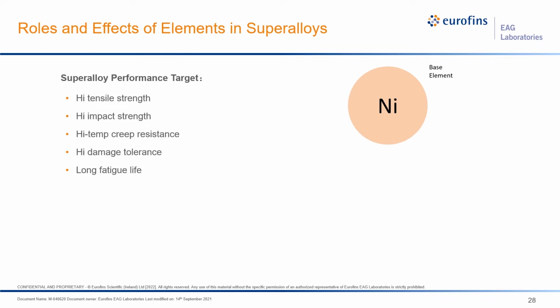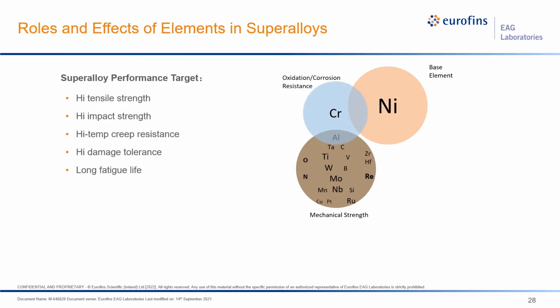Superalloys are used in a high temperature, high oxidation environment, so there are certain performance targets. They are nickel-based alloys and need to achieve high tensile strength, high impact strength, high temperature creep resistance, high damage tolerance, and a long fatigue life. But pure nickel doesn't have those capabilities, so we need to start alloying to provide mechanical strength with refractory metals such as titanium, tungsten, niobium, moly, rhenium, zirconium, hafnium, and many other elements in small amounts.